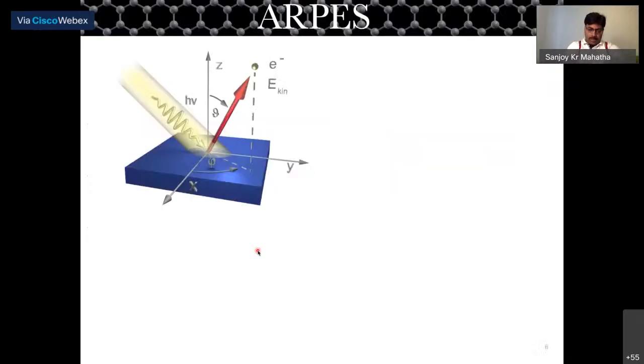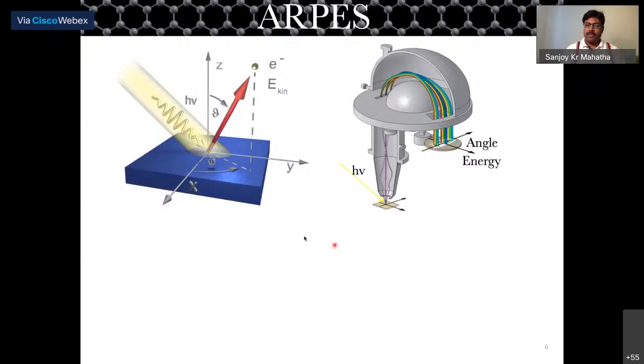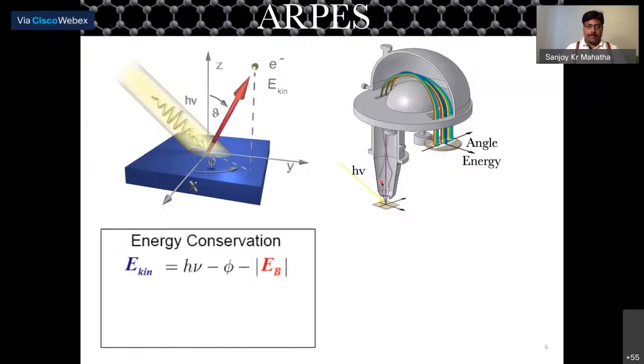We use angle resolved photoemission spectroscopy to study the electronic band structure of these materials near the Fermi level, or the valence band electronic structure. And this technique is based on photoemission spectroscopy. In photoemission, as we all know, when we shine a material with a sufficiently energetic photon, the electron will come out from the solid surface. By analyzing the kinetic energy of the emitted electron using this kind of hemispherical state-of-the-art analyzer and using the energy conservation equation, we are able to find out the binding energy of the electron inside the solid. So we measure the electron kinetic energy, h nu is the photon energy, which we know, and phi is the work function. It's a very simple equation, and we can easily extract the binding energy of the electron inside the solid.